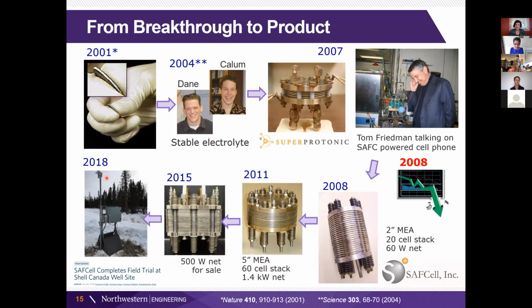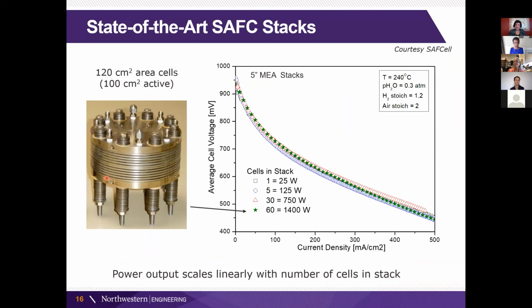In particular, I will show you some of the other things that have been done at the startup, is that we can make these stacks. And this is what you do to increase the voltage of the fuel cell, is that you make multiple layers. So once you pile them up in series with one another, then you get the high voltage. And so we can go up to a 1.4 kilowatt system, and it all scales really very nicely.